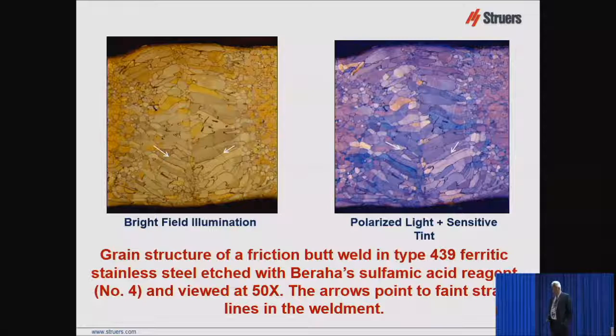On the left here, this is a friction butt weld in 439 ferritic stainless steel. We're using the sulfamic acid reagent number 4 that has the ammonium bifluoride addition so that we can do a grade like 439 ferritic stainless, which has a fair chromium content. And you can see in bright field, here's the center of the butt weld, and you see the grain structure and how the grains are elongated in the weld metal, the molten area. And then over here, we're getting to the original structure.